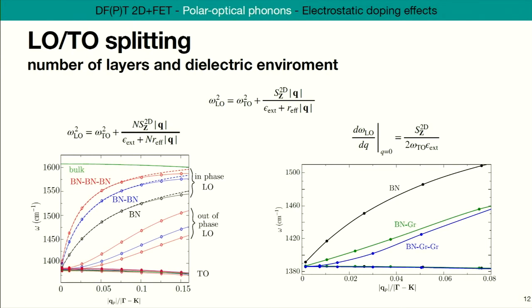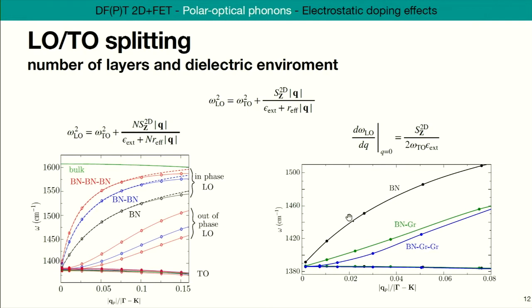The other interesting thing to see is that we already saw that at long wavelength, the screening comes from the environment. And that's something pretty peculiar that we can try and look at. So here we take BN again and put it on monolayer or bilayer graphene. The thing to know here is that monolayer graphene screens like a bulk dielectric material for some reason. Because of the Dirac cones and all this, you end up with the same kind of screening as a bulk 3D material. And so the effect is that the slope is divided by a constant, and this is what we see here. If you use bilayer graphene, now it screens like a metal, and you get a zero slope as you get to zero momentum here. And again, everything between the simulations and the analytical model fits rather well.